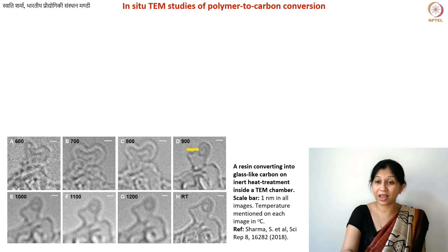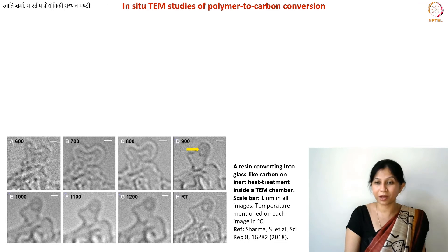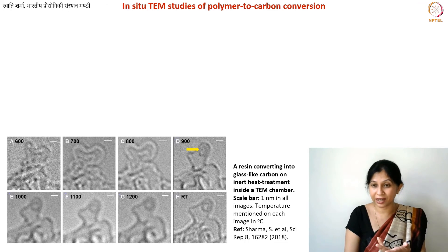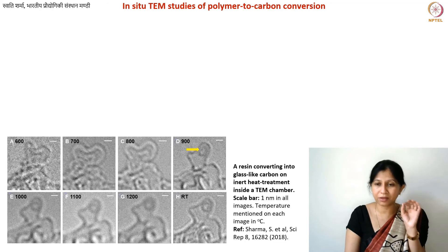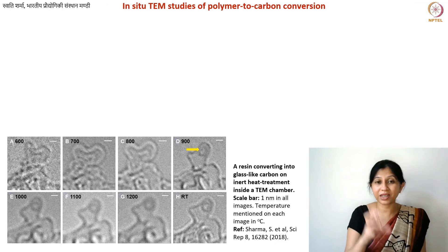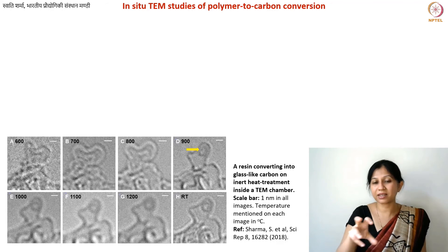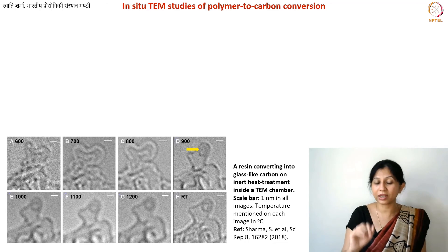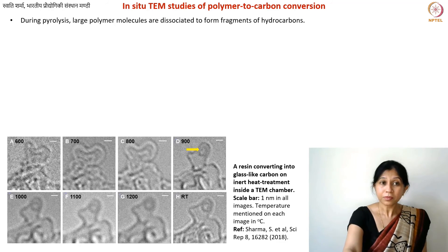At 600 degrees the material still has a lot of hydrogen — it is almost a polymer, not yet carbon. At 700 and 800 there are still many impurities. At 900 degrees you get reasonable carbon; electrical conductivity and mechanical properties all show a sudden change between 800 and 900 degrees, which is also clear from these images. The carbon structures become visible around 900 degrees, remain stable, and at room temperature after cooling from 1200 degrees there are minor additional microstructural changes as the material becomes more stable.